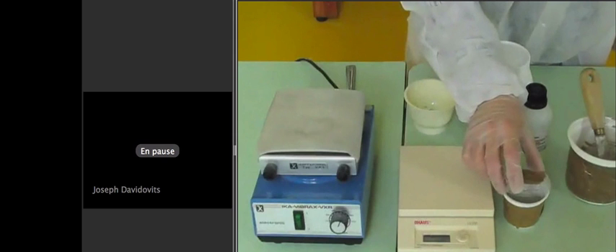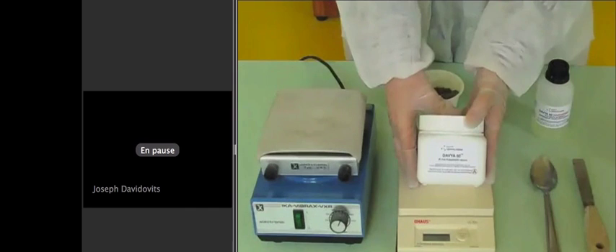So, what is the difference here? We have prepared the ingredients. We have the powder, that is metakaolin, slag and others, in powder form. This is one part. And we have prepared the hardener, that is our special silicate. The hardener is prepared separately and then mixed together. And then, this is the geopolymer binder, this is the geopolymer cement, slag, metakaolin-based geopolymer cement, and we add the aggregates, and we end up with a beautiful material.